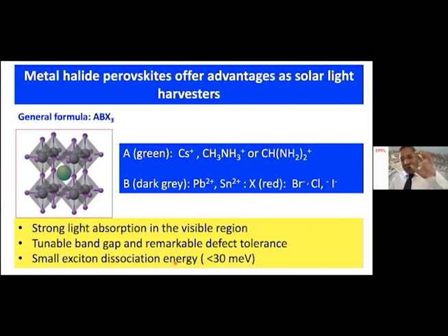This is very important. In many organic compounds, when you excite, you create an electron and positive ion pair. It's called an exciton. And then the exciton binding energy is quite high, and it requires energy to dissociate. In the case of perovskites, the moment we shine the light, the charges are created automatically and they are collected at the interfaces. So the binding energy is typically below 30 millielectron volts. It's insignificant. So there is an argument: do we have a short-lived exciton, or are we instantaneously creating the carriers to extract at the interfaces?